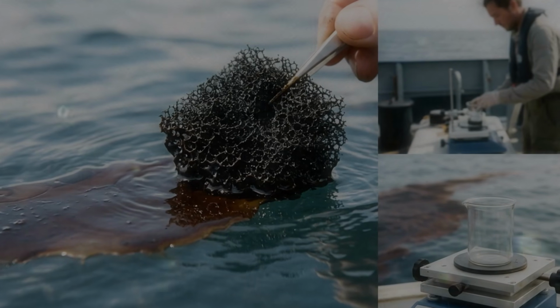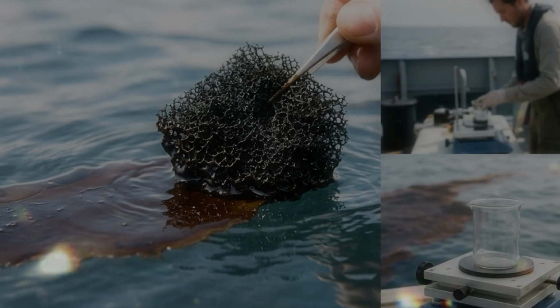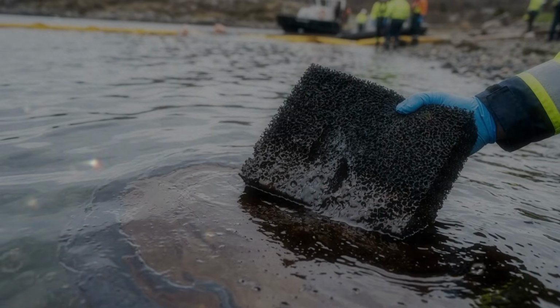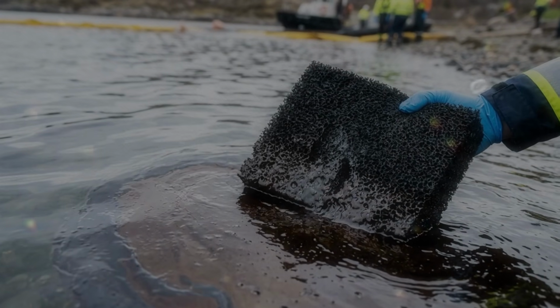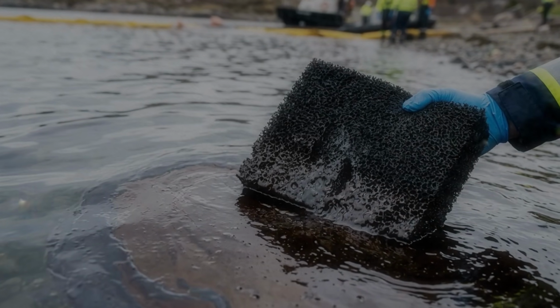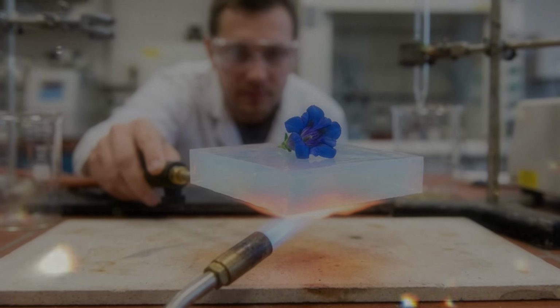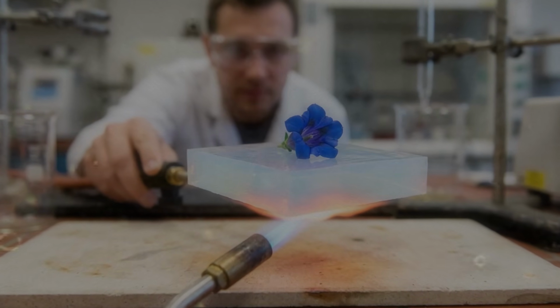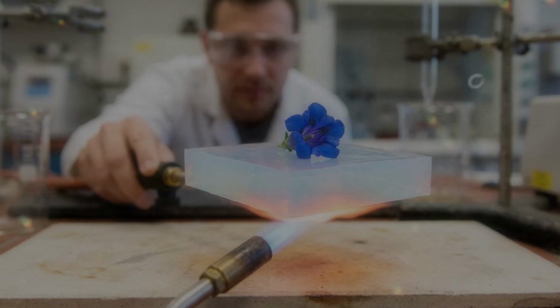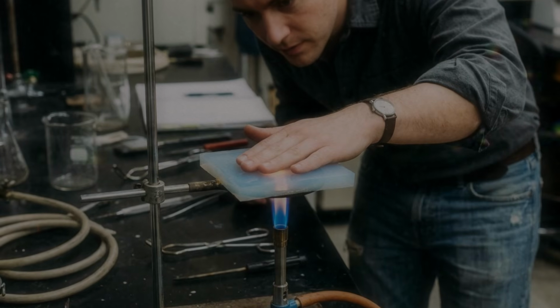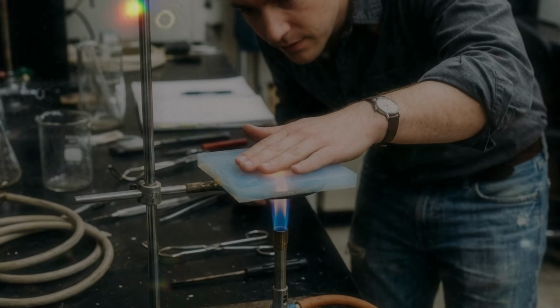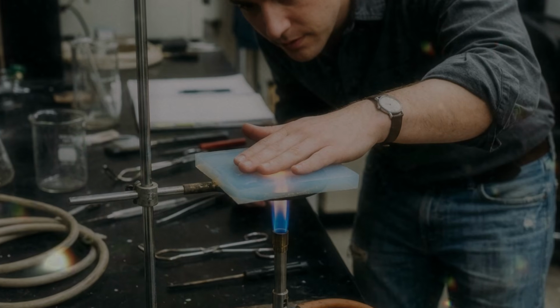Achieving consistent results requires careful chemistry and close control of the process. Commercial aerogel blankets are often made by forming aerogel within a fibrous support. The fibres provide mechanical strength, while the aerogel fills spaces between them. The finished material can be rolled, cut and wrapped around pipes or equipment more easily than a fragile monolithic block.